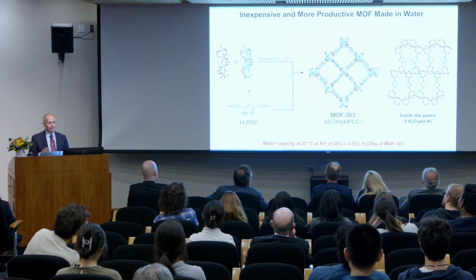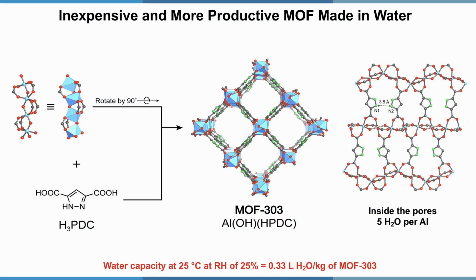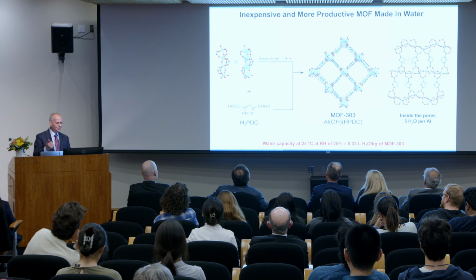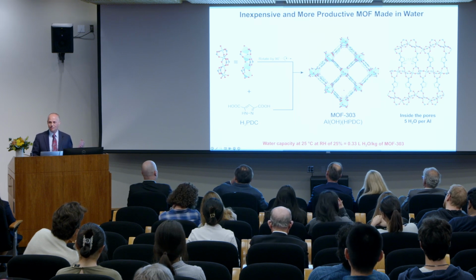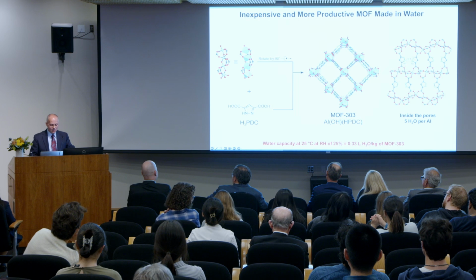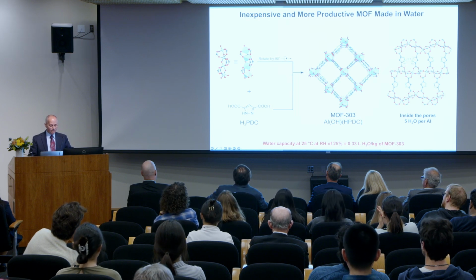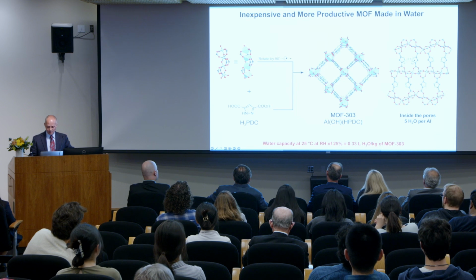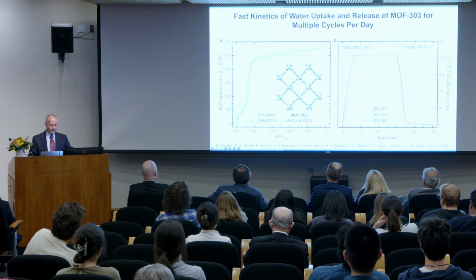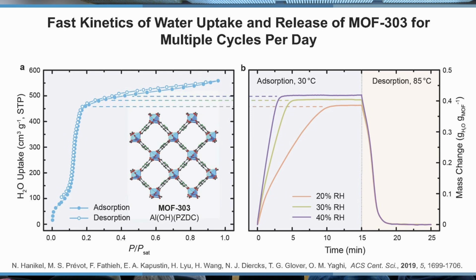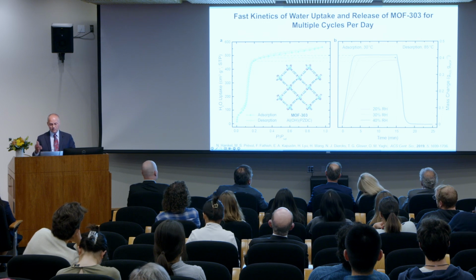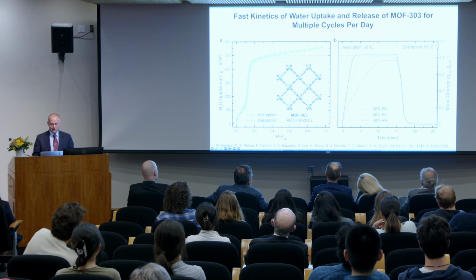Okay, so we reported that, and people said, well, zirconium is expensive. This MOF is going to be expensive. Zirconium is $160 a kilo. Well, again, chemistry comes to the rescue. We made aluminum MOF. Well, nothing is cheaper than aluminum. I mean, aluminum as a metal is inexpensive, $2 a kilo. We made a material out of that, and this material takes up water at even 10% relative humidity. Okay? It does so fast from low humidity, as well as if you really want to take the water fast out of the pores, you can heat to 85 degrees C. Within a few minutes, the water is out.